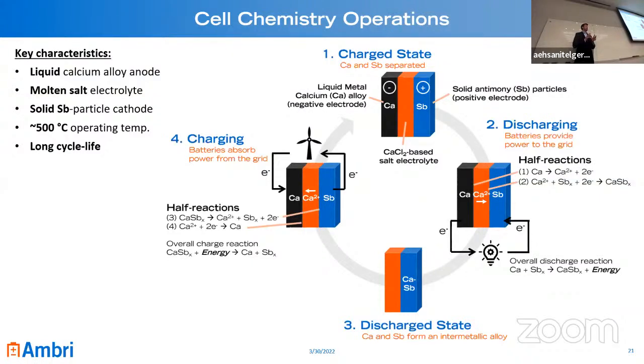The positive electrode, because the antimony itself is conductive, as long as it bumps into other antimony particles that have also bumped into the current collector, you maintain electrical conductivity to all those discrete particles. And so even if those particles fracture and break, we found we don't lose capacity in the system. You can retain capacity with the solid particle electrode. So no, we don't have to replace the antimony. It's part of the battery that lasts for those thousands of cycles. Okay, thanks. Thanks for the question.